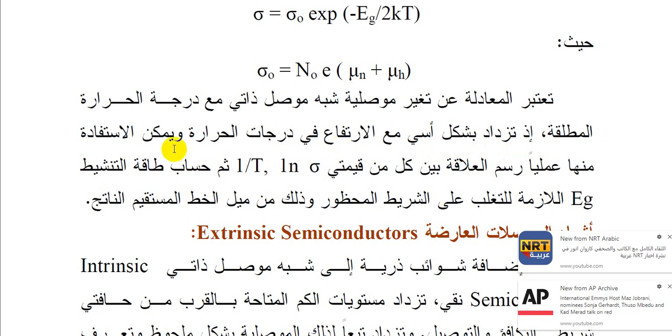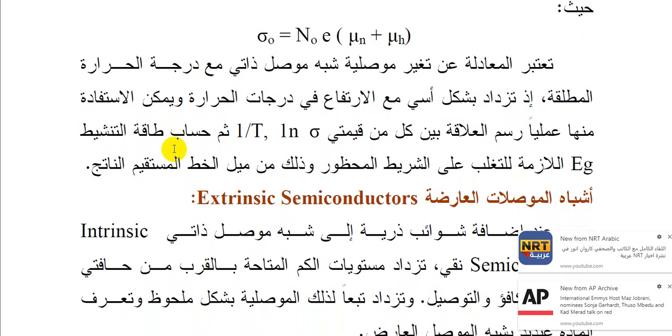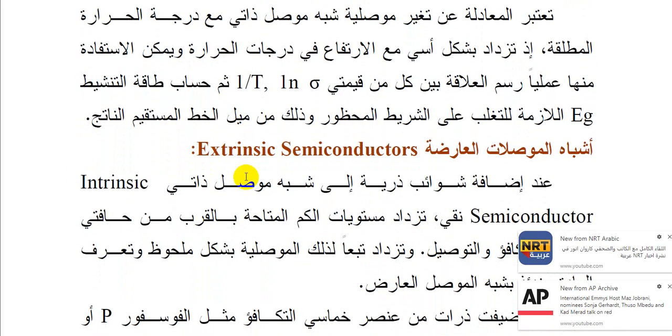exponentially with the elevation of temperature. This can be verified practically by plotting the relationship between the log of the sigma value and the inverse of the absolute temperature, then calculating the activation energy Eg required to overcome the gap from the resultant slope.